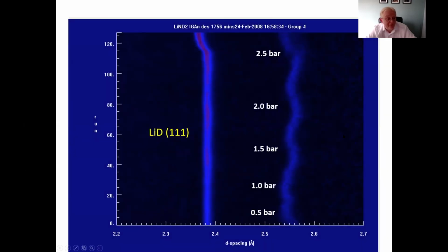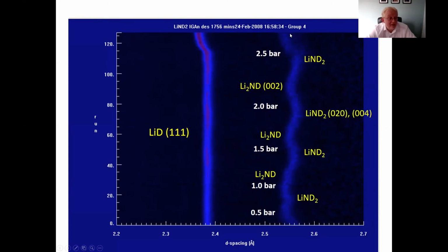But we can also follow that in the Bragg information, and you see this wiggle here in this line. This is not from any sort of movement of the sample. This is actually from it going amide to imide to amide to imide as we put hydrogen on, take hydrogen off, or deuterium in this case. And this shifting corresponds to that weight gain and weight loss.